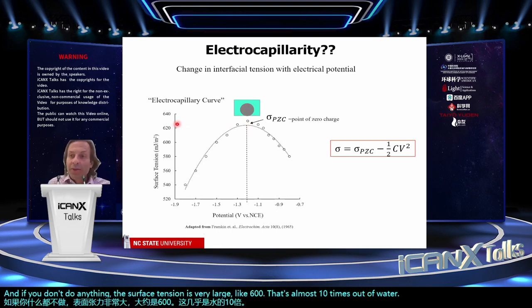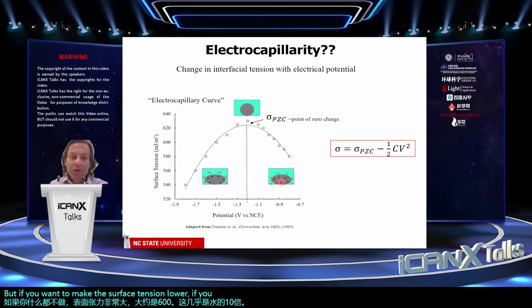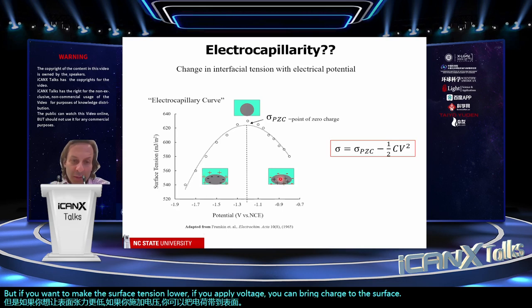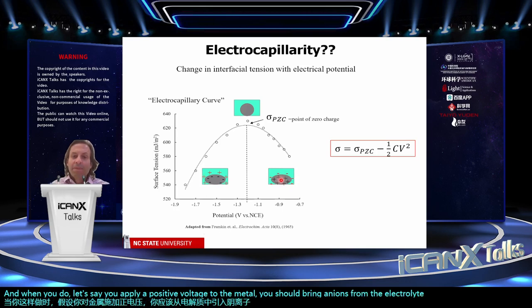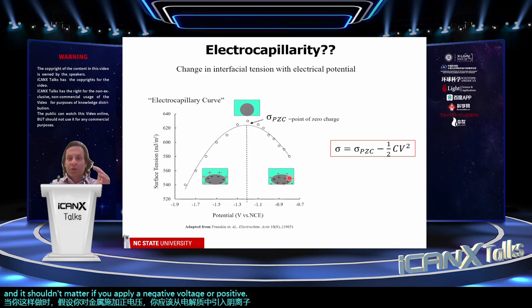But if you want to make the surface tension lower, if you apply voltage, you can bring charge to the surface. And when you do, let's say you apply a positive voltage to the metal, you should bring anions from the electrolyte to the surface. And it shouldn't matter if you apply a negative voltage or positive voltage. Either way, you should get a parabola.